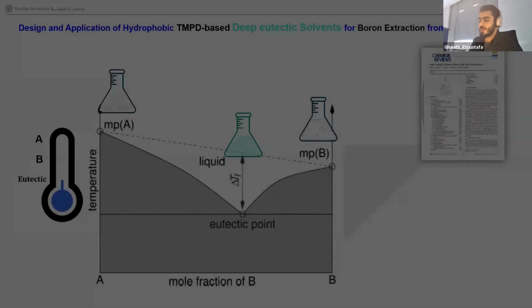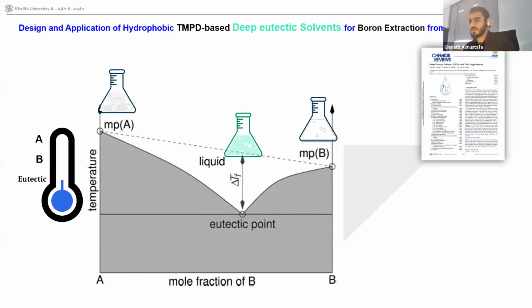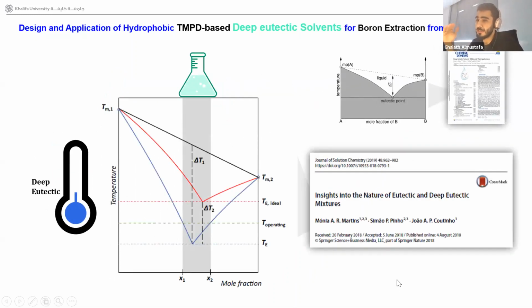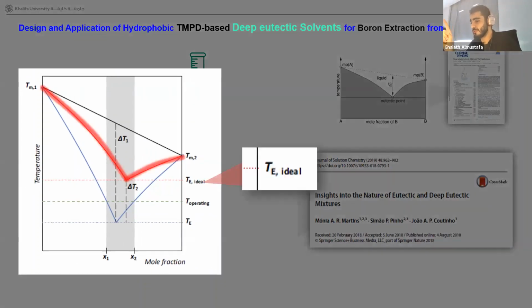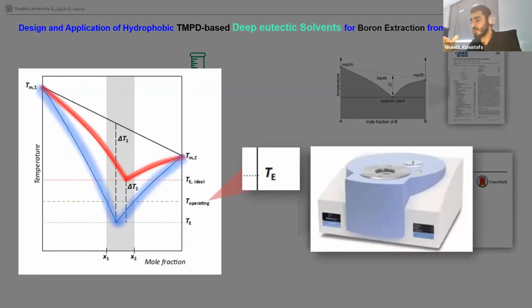Yeah. So we mix and shake those two components, and the resulting mixture has a depressed melting point compared to the individual components. Now, this is a very simplified version of deep eutectic solvents. This is the eutectic mixture. I want to just step aside and explain the deep eutectic part, which is basically defined through the deviation from the ideal behavior of two components mixed together, because any two components mixed together will behave differently. That deviation from the ideal temperature behavior is what we call a deep eutectic solvent. And this is what we measure experimentally, the deep eutectic part.